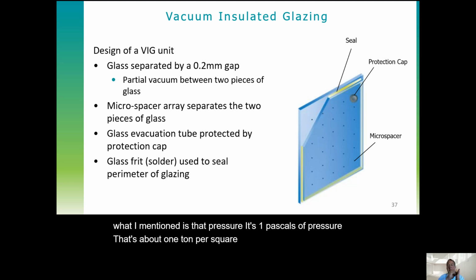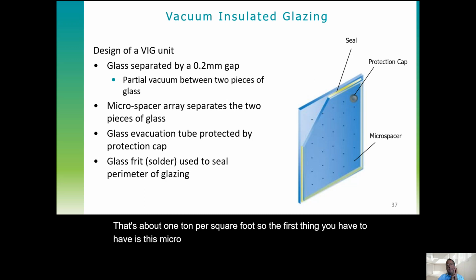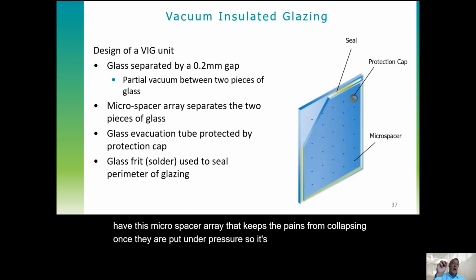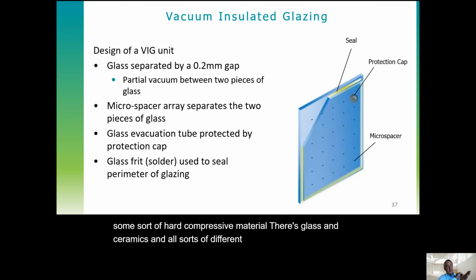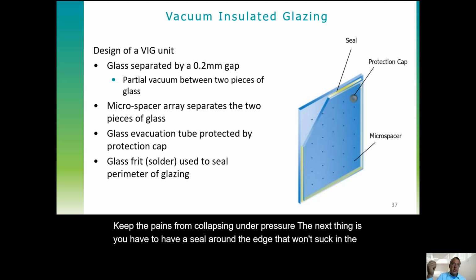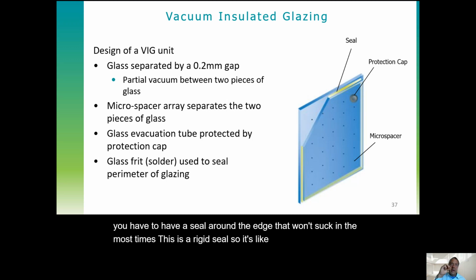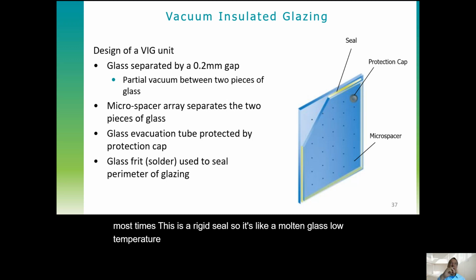So the first thing you have to have is this microspacer array that keeps the panes from collapsing once they're put under pressure. So it's this little tiny metallic or some sort of hard compressive material. There's glass and ceramics and all sorts of different ones that are used. But you have to have something that's literally every inch across, or inch and a half across that entire face to keep the panes from collapsing under pressure. The next thing is you have to have a seal around the edge that won't suck in. So most times this is a rigid seal, so it's like a molten glass, low temperature molten frit, or it could be like a metal weld that you're literally welding the edge shut.